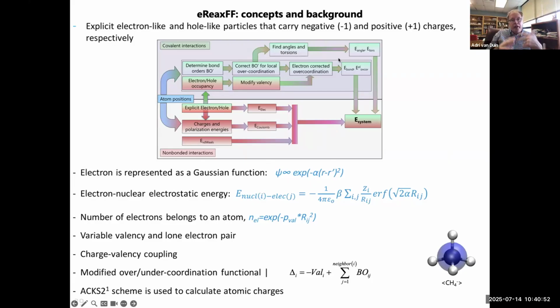However, if we transfer charges and transfer a full electron, then clearly the valency of the atom should change. In CH4-, for example, the carbon has an extra electron. CH4 is clearly stable for neutral carbon, but it's very unstable for the CH4- radical anion, and it will almost directly break a CH bond, because now carbon is isoelectronic with nitrogen, and for nitrogen, clearly NH3 is more stable than NH4.